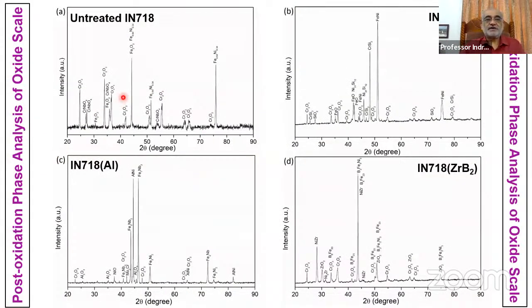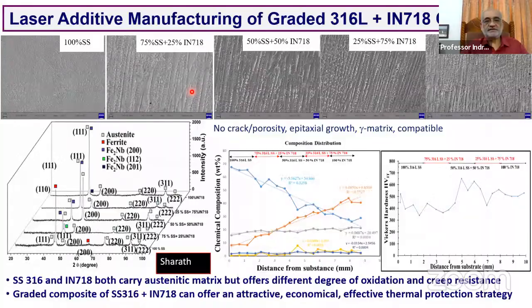What is also interesting is that if you look at the post-oxidation XRD analysis, you realize that this phase aggregate not only has oxides, but also some of the pristine intermetallic phases. So in other words, despite exposure for 100 hours at a fairly elevated temperature, you are still left with unconsumed or unconverted intermetallic phases. That means these intermetallic phases, because of their high stability and high melting temperature, are still not oxidized, and they can continue to give you a good amount of oxidation resistance.